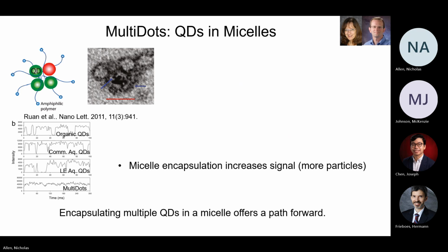So here you can see the particles that we made have an intensity of about 40,000. This is over time, just showing you the fluctuations. When we took those same particles and just did a method called ligand exchange, where we took off the organic ligand on the surface and replaced it with a water-soluble one, this is only 4,000, and we have multiple incidents of what's called quantum blinking, which is where they just lose fluorescence for a minute. They look like stars. They fluctuate. It's kind of fun to watch, like a record or something.